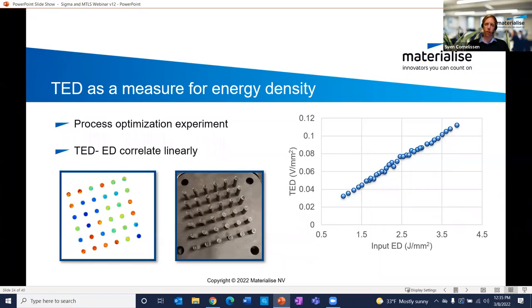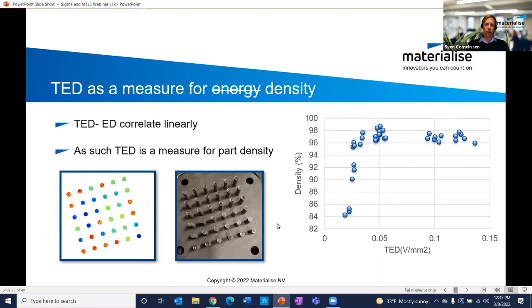And later on, when we talk about closed loop control, you can also use it for controlling towards the right value of energy density as a consequence of this. And as you probably know, of course, energy density is not the only metric for making high quality samples, but it's definitely true that if your energy density goes outside of your ideal processing window, then it will have a huge influence on the density of your sample. So in a way, this thermal energy density is a good indicator also for the density of your parts.